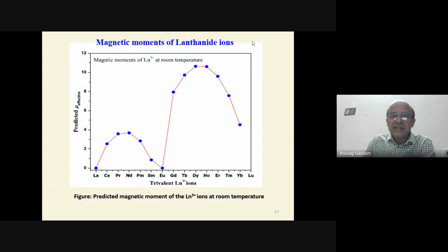And this is the magnetic moment of the lanthanides, and you see here how much it is. Why are we using gadolinium? Gadolinium already has 8 emu. This is the magnetization of gadolinium in Bohr magnetons. So gadolinium is already 8 Bohr magnetons, and the highest is dysprosium. So dysprosium and holmium can both be used as T2 contrast agents, because gadolinium has the highest number of unpaired electrons. One more parameter is the TE, as they call it, that is how fast,